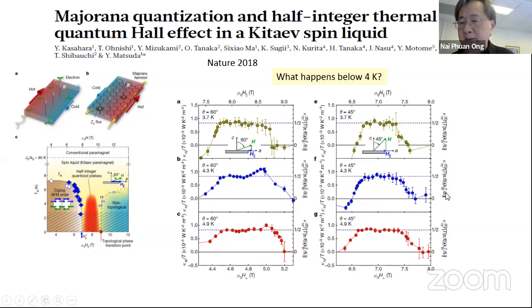But the data stops at 4 Kelvin, right? And this has been a deep puzzle to many people, because quantization of a transport current generally gets better and better as you cool down to sub-Kelvin temperatures, right? As we learn from the quantum Hall effect. Here, there's absolutely no data below 4 Kelvin. Well, a shade below, 3.7, but that's where the data stops. And so it's sort of interesting.